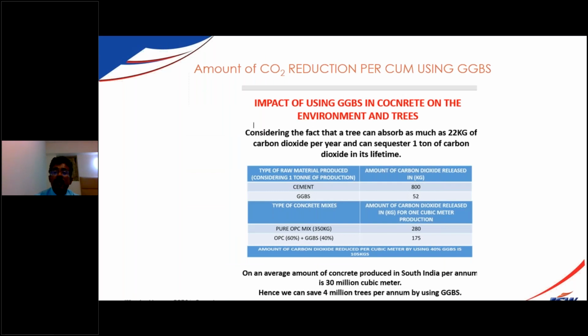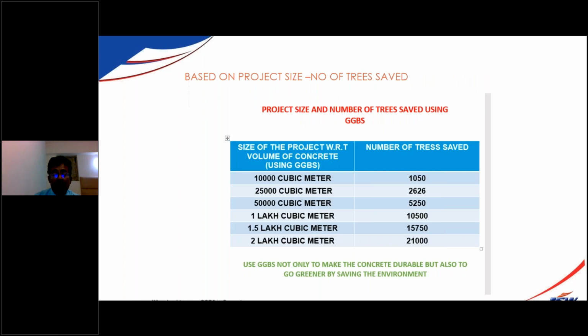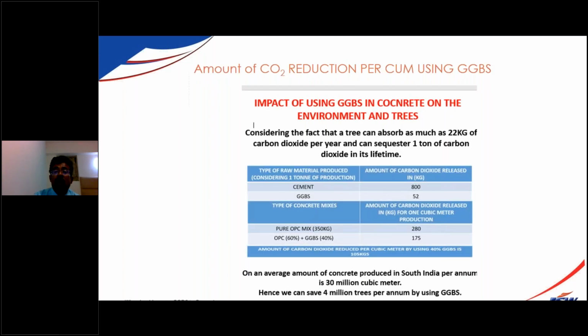I've done a small calculation by using 40% replacement for a 350 mix of concrete, how GGBS can reduce the carbon footprint. For every cubic meter of concrete, 105 kg CO2 emissions is getting reduced. So based on that calculation, we have done a thing. The basis is that one tree can absorb 22 kg CO2 per year. So in its lifetime, it's going to absorb only 1 ton of carbon dioxide. So that means to say, if I make concrete with 40% replacement of GGBS, it can reduce 105 kg per cubic meter of concrete.